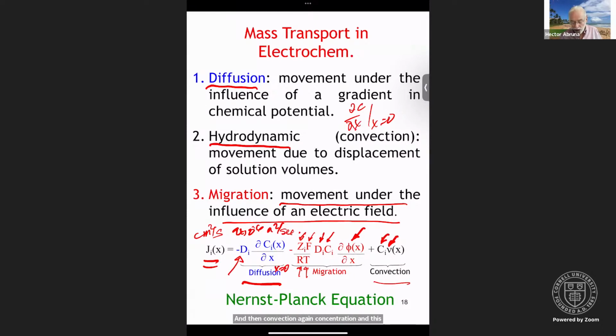We will be considering one-dimensional flux to the electrode surface when we talk about rotating disk electrode measurements. As we'll see later on, you can describe diffusion and convection with great mathematical rigor. The contribution from electrical migration is a lot more complicated. And so in order to accommodate for that, what we typically do in electrochemical experiments is add a so-called supporting electrolyte that has two effects.